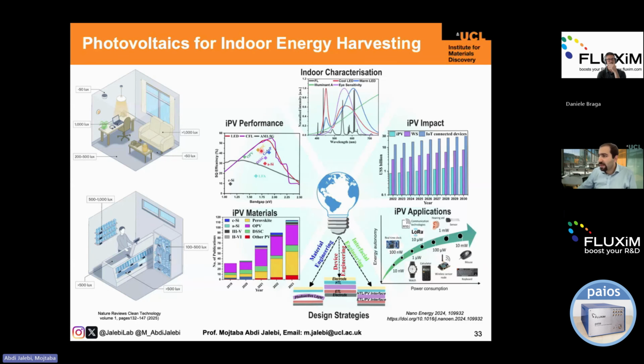As you can see, you can reach quite high efficiency with perovskite solar cells, almost higher than the other technologies. This is showing a maximum of close to 60% in indoor light conditions. And this is also showing the number of publications over the years. As you can see, perovskite had a small share at the beginning back in 2019, and nowadays is almost surpassing organic photovoltaics.